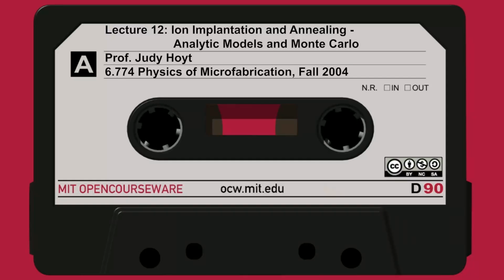So this is assumed to be as implanted, the red, assuming a very simple Gaussian distribution with a certain standard deviation, delta RP, and after it's gone through diffusion, is shown here in the blue. The peak has dropped, and now it has a new standard deviation, which is delta RP plus the square root of dt. So this gives us an idea of how we can evolve an implanted Gaussian during a diffusion step.